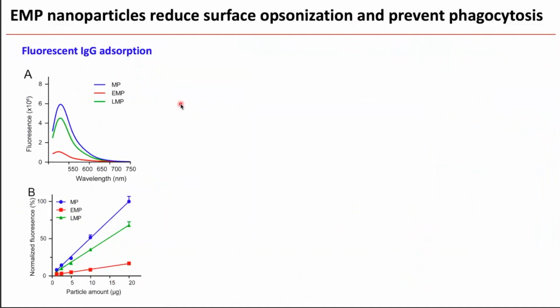In this slide, we are showing these EV enclosed nanoparticles reduce surface protein adsorption. In this particular case, we are using fluorescent IgG, and we are comparing the EMP nanoparticle, the nanoparticle coated with the EV membrane, and also the nanoparticle coated with the liposome. In this case, it's very clear that after coating with the EV membrane, the IgG adsorption is significantly reduced.